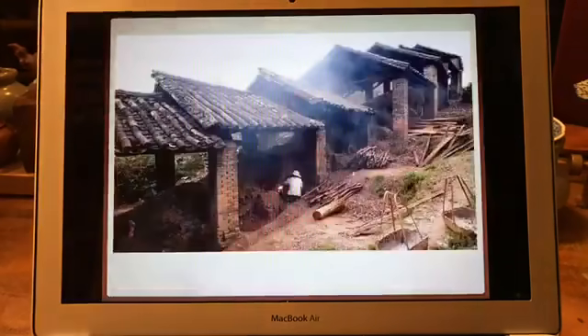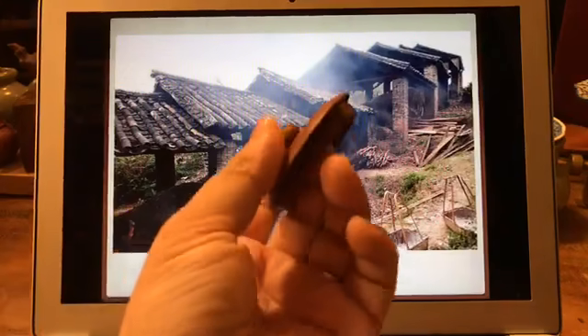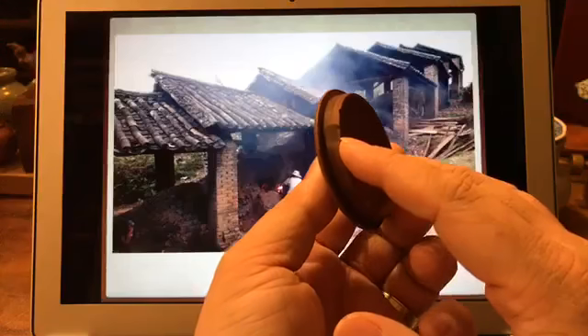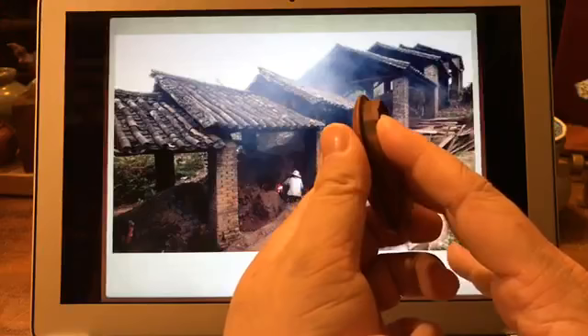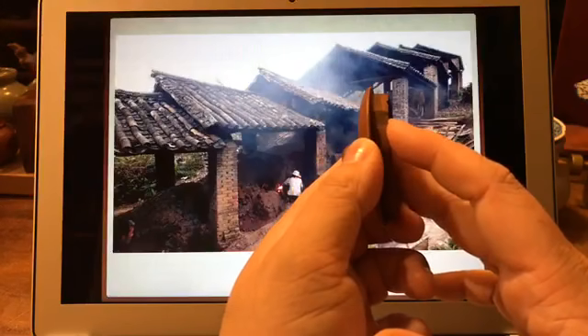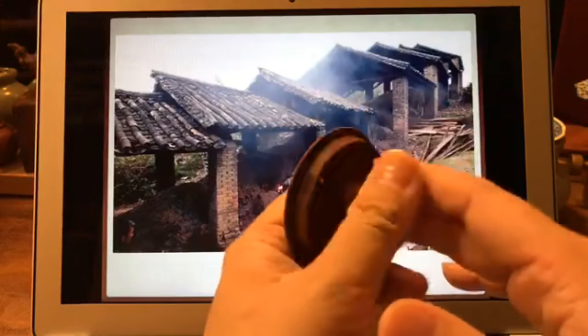Yep, so the typical dragon kiln, you can see, this is not firing, and the dragon kiln itself is complicated. This will also eventually link into why people say that some of the Qing dynasty pots have what we call black bone, or hei gu, which means that when you crack or chip an early era Yixing pot, you find that although it's a zhuni or red pot, when you crack it, you actually have a dark purplish or dark blackish interior.